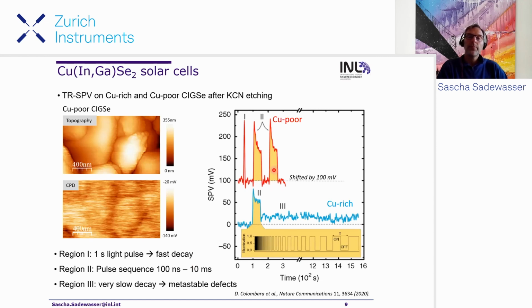And then after switching off again, this goes back to zero. However, for the copper-rich material, we see a similar behavior, first an increase, then it drops during the sequence, and then a sharp drop as the sequence finishes and we are in dark conditions again. But it doesn't fall down to the initial zero value here, but there's a very slow decay over longer time. And this long decay is due to metastable defects.